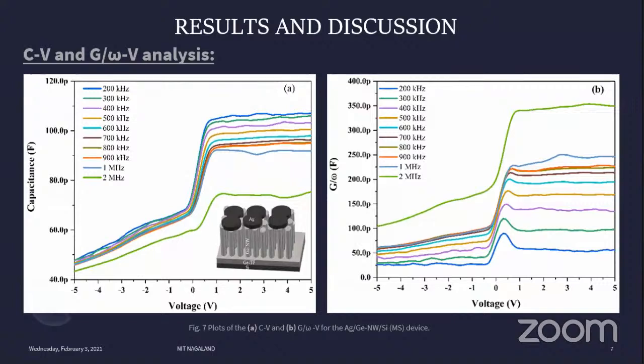So in the discussion, we have carried out the capacitance and conductance analysis using Keithley 4200 SCS. If we look at figure 7a, we can see that the capacitance measurement has been carried out from 200 kilohertz to 2 megahertz. In this frequency range, we observe that with this kind of device structure, there is a decrease in the capacitance value as we increase our frequency. This is primarily speculated to be because of the presence of series resistance as well as surface states or interface state densities. Moreover, we can see that there is a dispersion in the depletion region as indicated here by the cursor. This is also primarily because of the surface states present in the device structure. This is the schematic of the device.